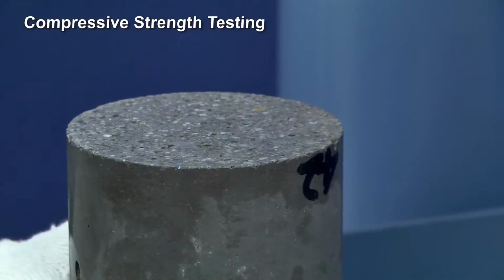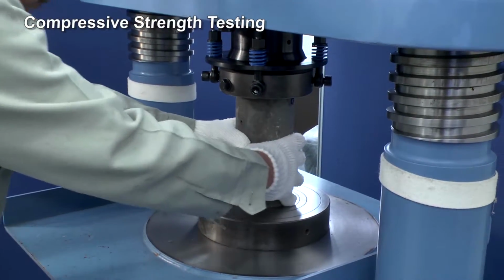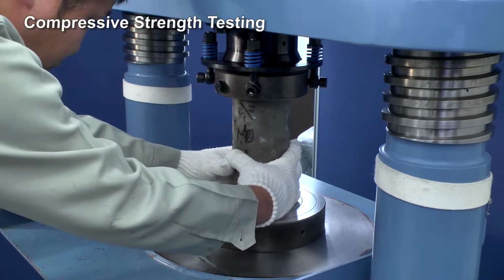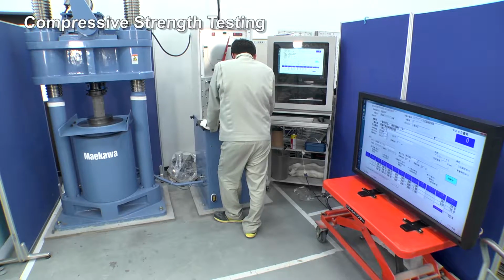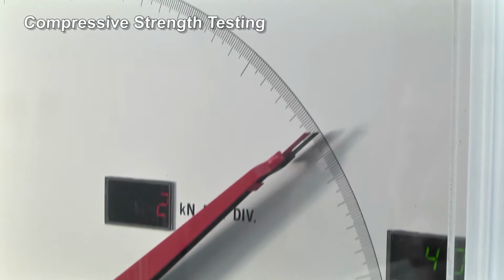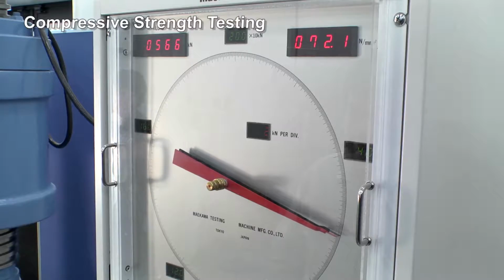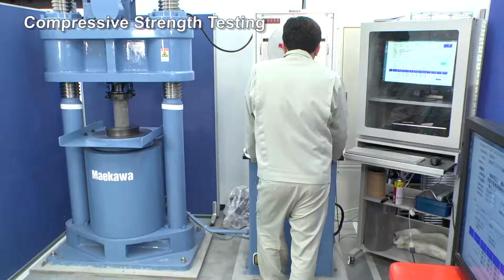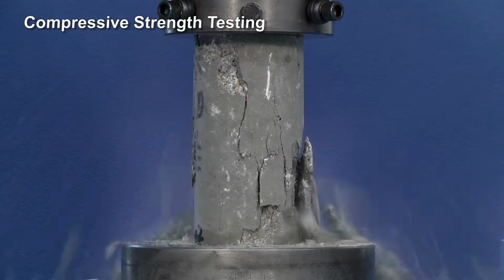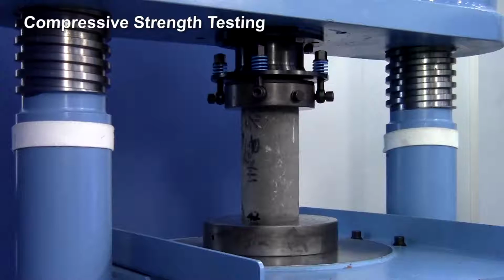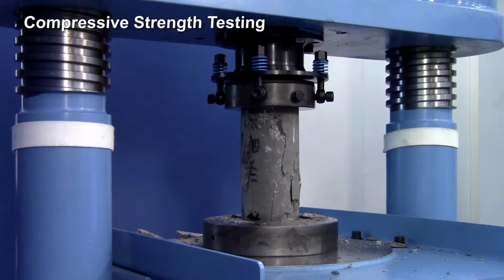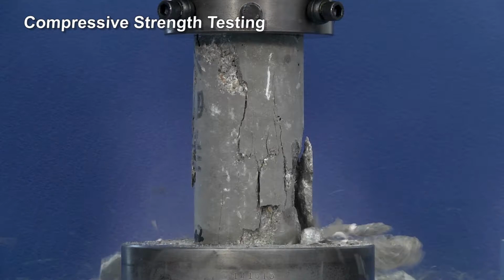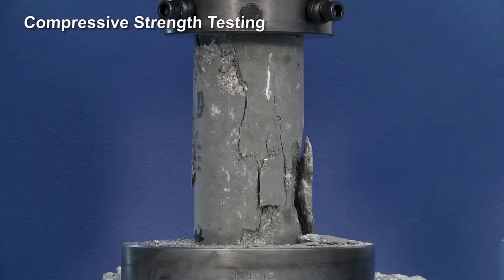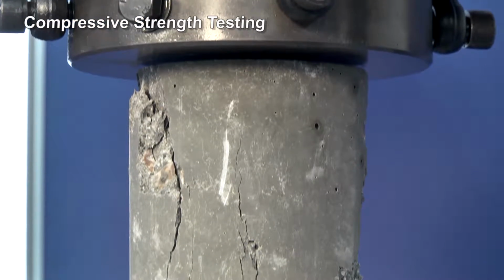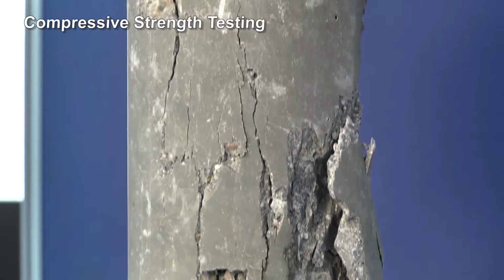For compressive strength tests on concrete, at the Musashi Fuchu Test Laboratory, the maximum load is up to 3,000 kilonewtons, while the other test laboratories can provide a maximum test load of up to 2,000 kilonewtons. When pressure is applied at a given speed, at some point the test specimen breaks. Normally, 3 specimens are tested in this way, and the average is taken.